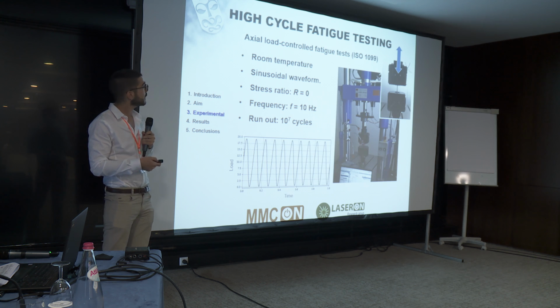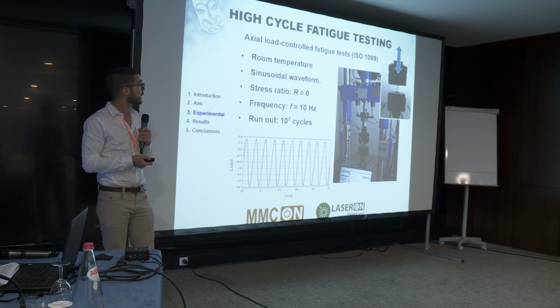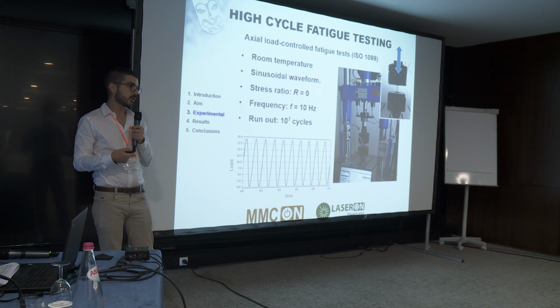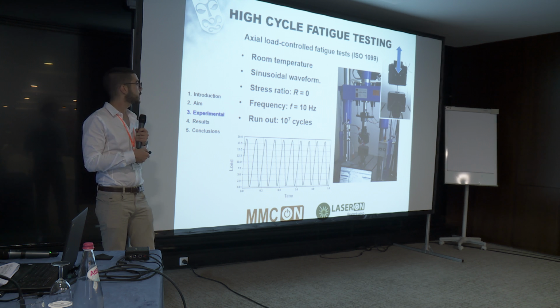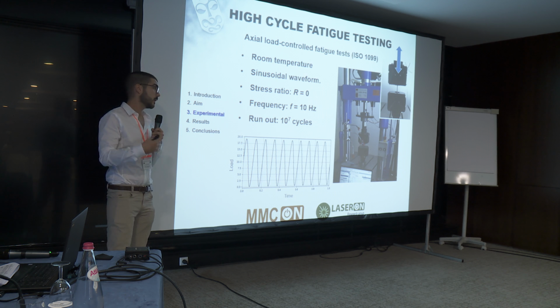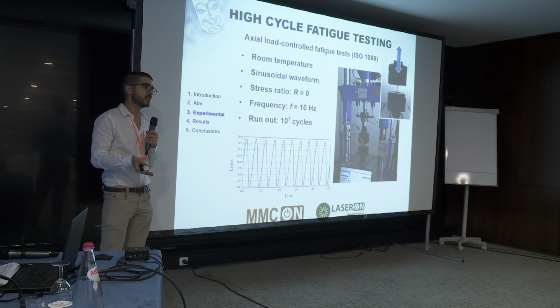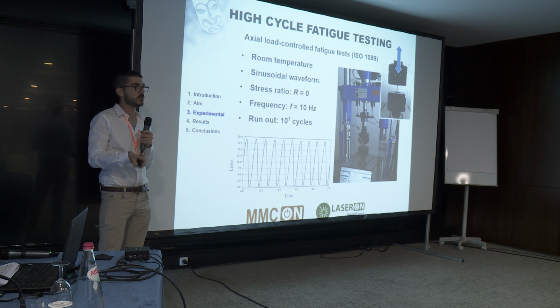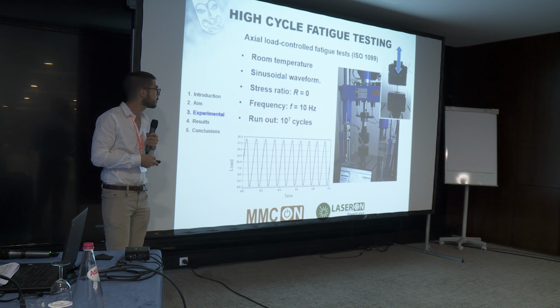The high cycle fatigue tests that we performed were axial load control tests with a stress ratio equal to 0 and 10 Hertz of frequency. And we performed these tests until either failure of the specimens or reaching 10 million cycles.